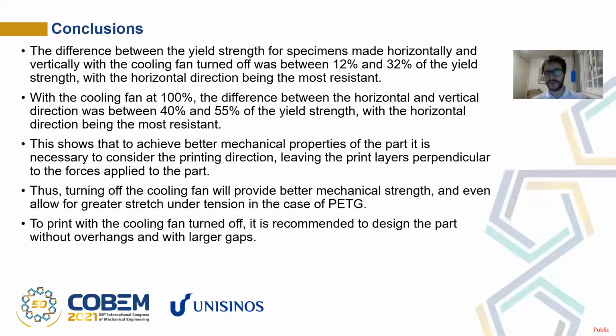So the difference between the yield strength for the specimens made horizontally and vertically with the cooling fan turned off was between 12 and 32% of the yield strength, meaning that printing a part with the layer lines perpendicular to the force is stronger, even with the cooling fan turned off, around 12 to 30%. And if we use the cooling fan at 100%, the difference between the horizontal and vertical ones is even higher, being around 40 and 55% of the yield strength, just by changing the layer orientation.